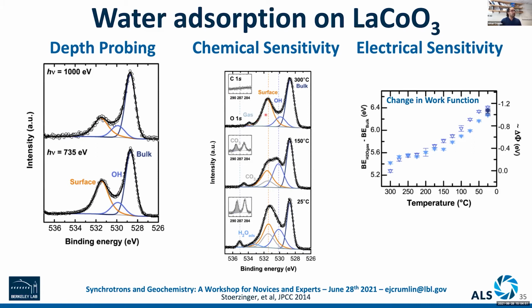The fittings here are able to help really clarify the type of chemical changes that are taking place as we are making these changes to the sample. But we're also, again, getting this electrical sensitivity because we're seeing some shift to the gas phase of the water feature that's here. What that is actually telling us is how the work function of the sample interface is changing. And this is something we can get directly from the electrical sensitivity that this technique provides us.